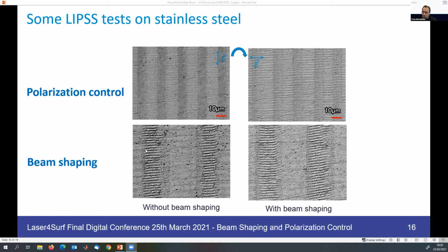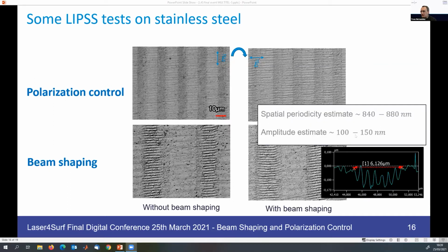Regarding beam shaping, you can see here the LIPSS obtained with the Gaussian beam, and here the LIPSS obtained with the flat top generated by the DOE, which is much more regular than what we can get with the Gaussian. In this case, we have about 800 nanometers periodicity and a depth of about 150 nanometers.